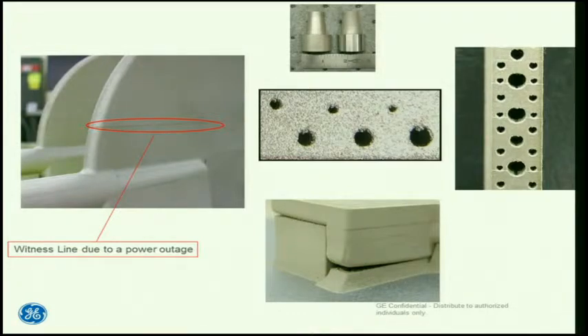The other thing that you'll get is small holes. You'll tend to get horizontal holes built horizontally, so the layering going this way and the hole this way. You'll get little stalactites coming down from the top, and that's because in the case of the laser-based processes, the laser picks up a little bit of the particle underneath and you don't have a supporting layer underneath it. Those are some close-ups of some parts. They're not perfectly round holes. They tend to have a little bit of goobers up there at the top.